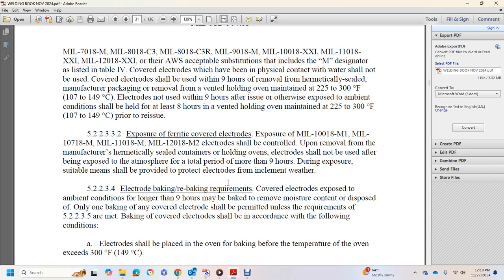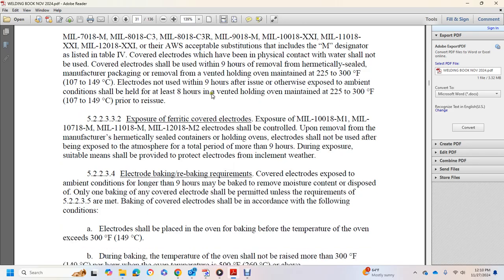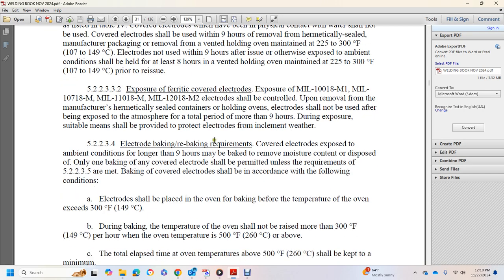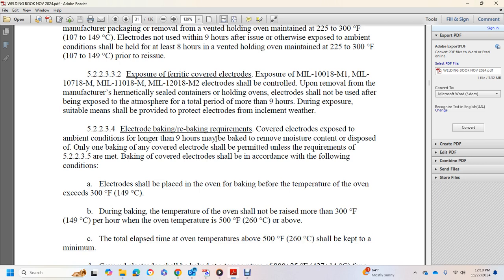Only one baking of any covered electrode shall be permitted unless the requirements of 5.2.2.3.5 are met. Baking of covered electrode should be in accordance with the following conditions. Electrodes shall be placed in the oven before the temperature of the oven exceeds 300 degrees Fahrenheit. During baking, the oven temperature should not be raised more than 300 degrees Fahrenheit per hour when the oven temperature is 500 degrees or above. The total elapsed time when the oven temperature is above 500 should be kept at the minimum.